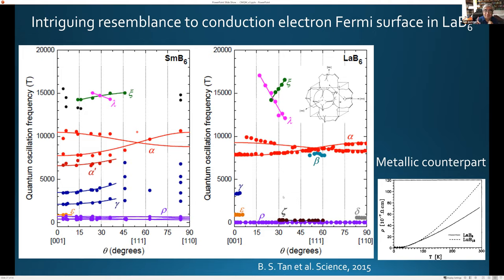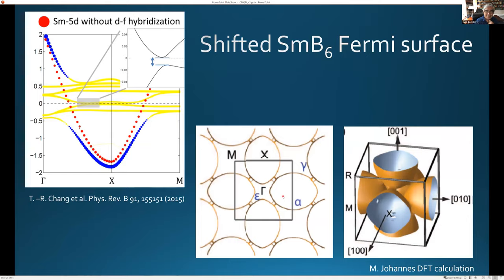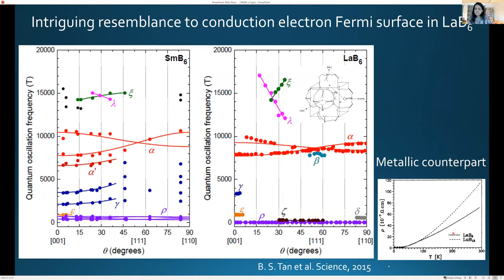So this is just a question, yes, if I may. Yes. So how does the resistivity of lanthanum hexaboride compare with samarium hexaboride? Yeah, that's a really good question. So it's down here on the right. Sorry, I should have pointed to it. It's that of a very good metal, right? So it doesn't go up as you would expect for an insulator. It goes down. And we have measured oscillations in the lanthanum hexaboride. They're very, very large amplitude, and the mean free path is very high. So it's essentially a very good metal.